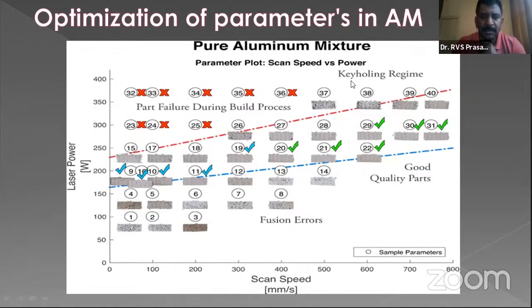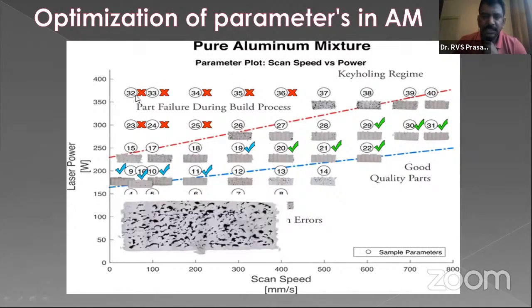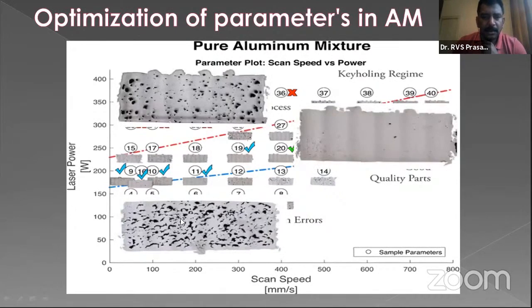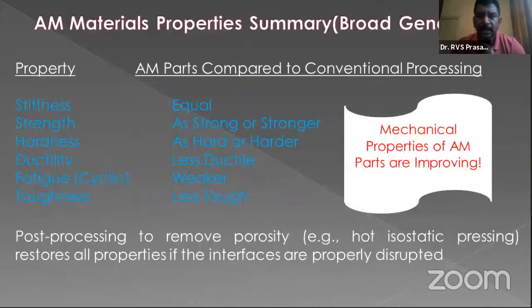So maybe all these experiments may become waste, because unless you do the optimization, you don't know what particular region is good for a particular material. So in this experiment on the pure aluminum mixture, you can see clearly these are the fusion errors in this zone, and you have a lot of porosity in this particular zone. However, in this particular zone, you will be getting better quality parts.